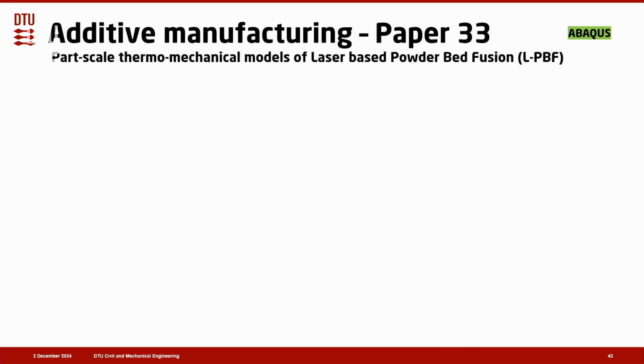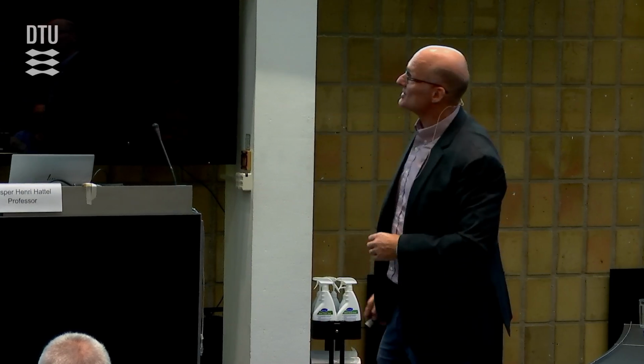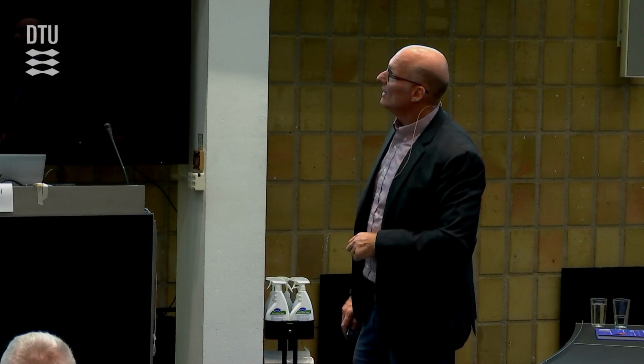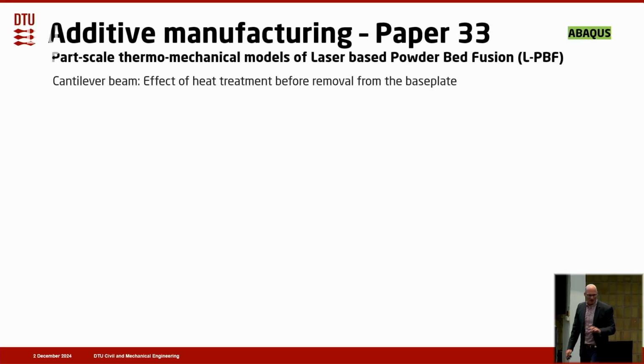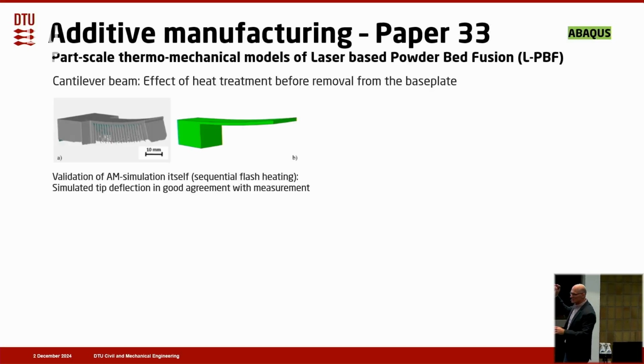This was the one that was closest, of course, because it had the highest refinement. So via refinement, we get better results. That's not surprising. Then we looked at a cantilever beam that was heat treated. So we wanted to see the effect of heat treatment before removal from the base plate. We did a validation of the additive manufacturing simulation simply by comparing the tip deflection of the measured part with the simulated part.